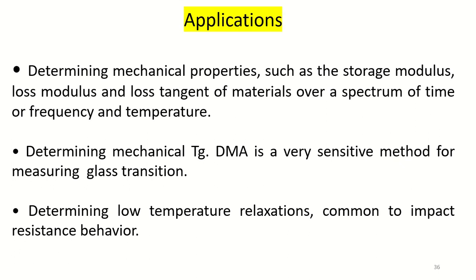The second one is determining the mechanical glass transition, which is denoted with Tg. Dynamic mechanical analysis is a very sensitive method for measuring glass transition. It is especially indicated for some polymers that show a slight change of heat flow at glass transition Tg, so that it cannot be seen by differential scanning calorimetry, DSC. The reason is that their content in the amorphous phase is small. Nevertheless, even in those cases, the stiffness changes sharply at glass transition.